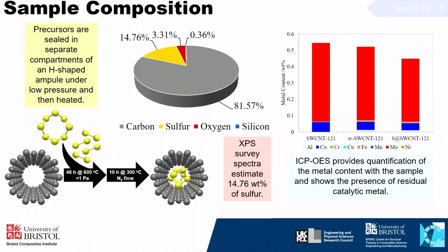As for the metal content of our materials, we've also done a few bits of characterization, looking at optical emission spectroscopy. What we're paying particularly close attention to here are the ferromagnetic impurities, something like iron, nickel, or cobalt. And what we can see is some residual catalyst left over from the manufacturing.